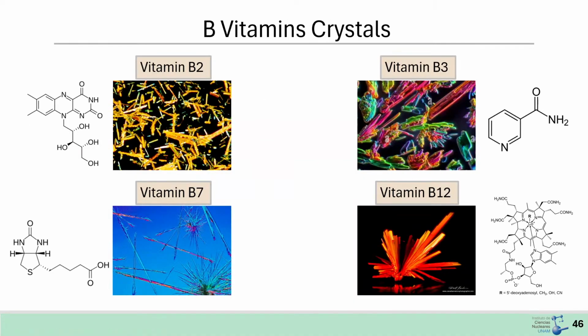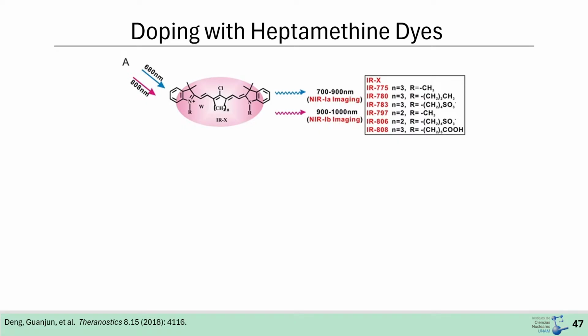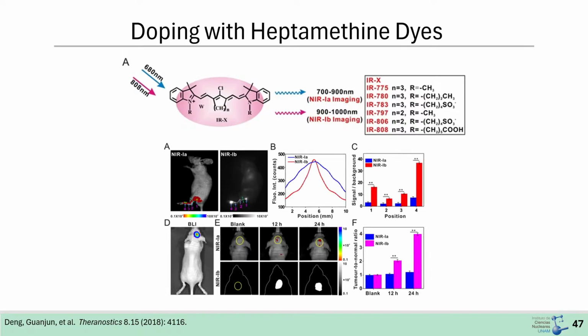So the biocompatible crystals can be of bio-origin, or can be synthetic, such as vitamins B, and those are materials that I'm interested in starting with. They also can be shaped into these rod-shaped particles, and they can be doped with organic dyes. Those organic dyes can be excited and emit in the biological windows. For example, in this study, they injected the dye directly and could do imaging, and they showed that there is a low cytotoxicity. Nonetheless, if we use this dye only as a dopant, we reduce significantly the amount of the dye and we put it in vitamins B that our body needs to develop for the brain, for the cells, we can reduce significantly the cytotoxicity.